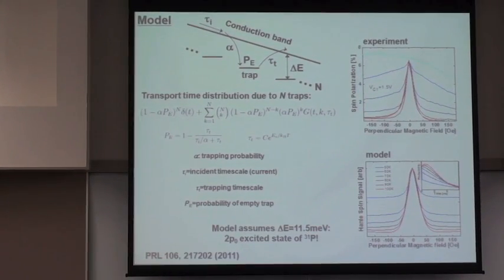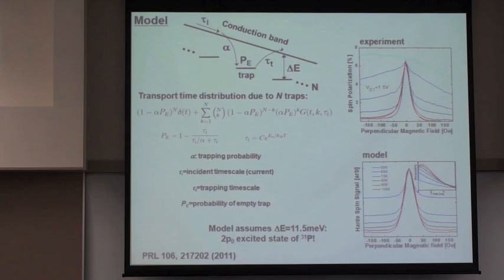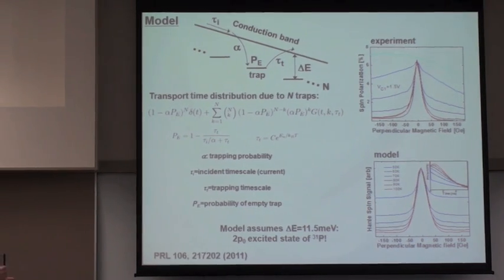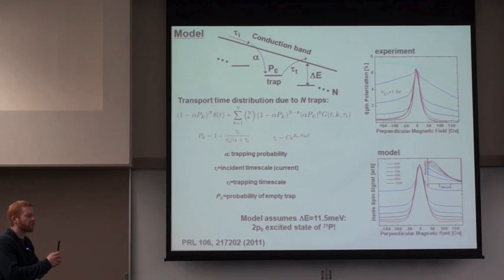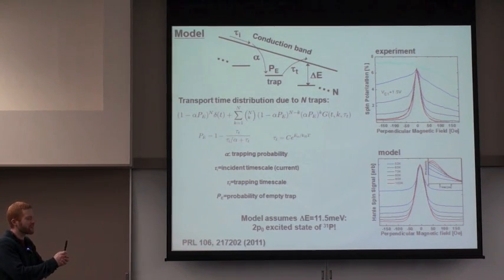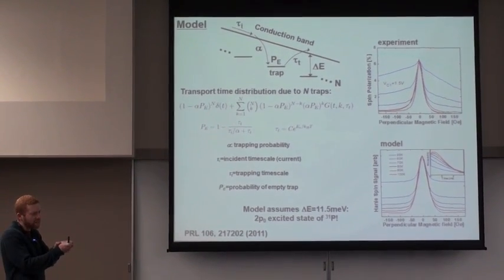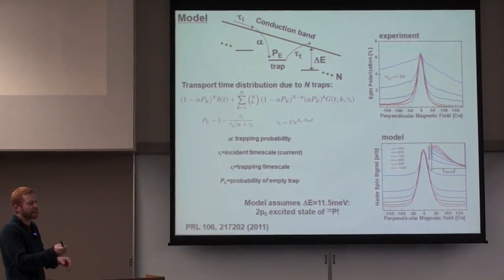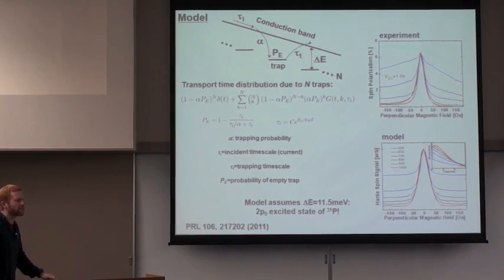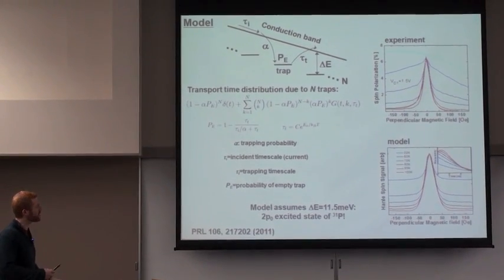Now, this is why you may have noticed in a previous slide I described our ability to convert between the magnetic field measurements we make and the transit time distribution as a Larmor clock. Essentially, under the influence of this Larmor precession with the magnetic field, the electron's spin is actually acting like the hands of a clock. We're injecting electrons all set to zero time, and the hands of the clock start moving, and we measure the angle of the hands of the clock at the detector. So they retain their measurement of what's happening in between injection and detection.